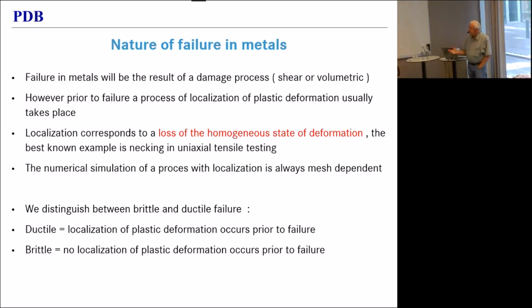So failure in metals will always be the result of some damage process. But prior to that failure, we will usually see a process of localization of plastic deformation. That means we lose the homogeneous state of deformation. We localize plastic deformation in a small area. And that localization, when we simulate it, will inevitably be mesh dependent, which is why we need regularization.